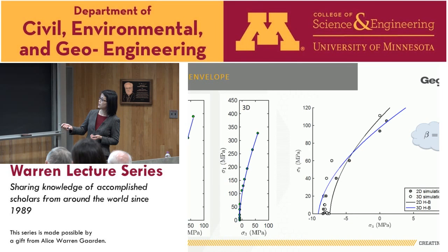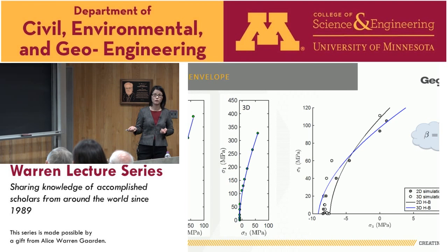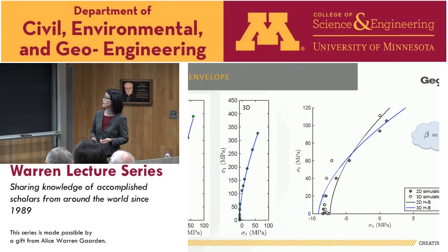For 2D, it's perhaps up to a confining pressure of about 20, and the tensile strength over here is around 6 and 7. So 20 divided by 6 and 7 is in the ballpark of 2 and 3 for 2D. For 3D, all the way up to perhaps slightly less than 60, with your tensile strength being 6 and 7, it's about 7, 8 times. So I was actually very surprised that with numerical simulation, we are producing results consistent all the way back to those from Griffith.